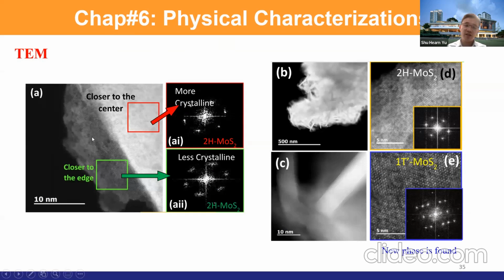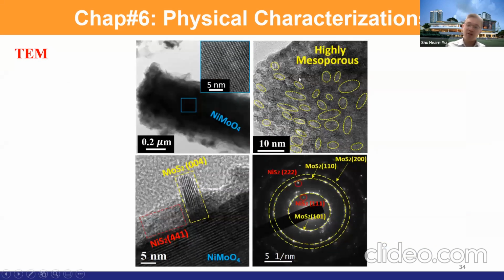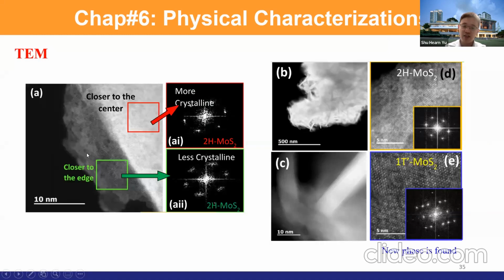So we find that if the TEM is taken close to the center of the crystal and close to the edge of the crystal, the crystallinity is different. Close to the center, we have more crystalline structures, and close to the edge, we have less crystalline structures. You can see that these diffraction spots are more diffuse. This is good for us because this result is aligned with this result. You can see this is mesoporous. It's less crystalline, and these are active sites for the HER reaction.